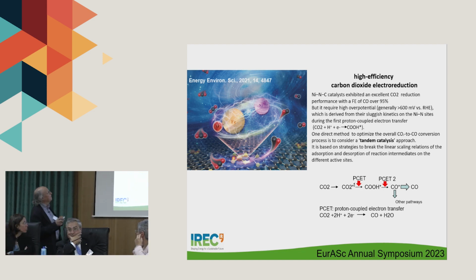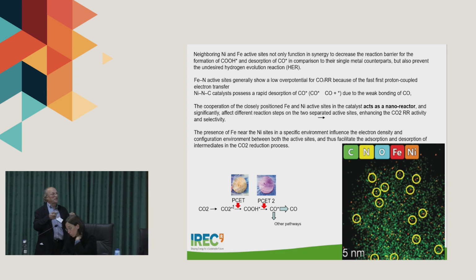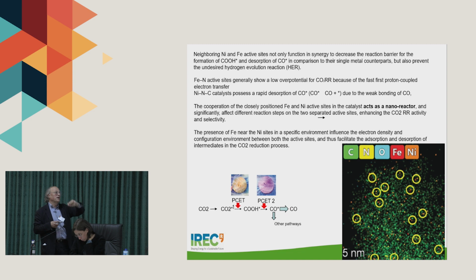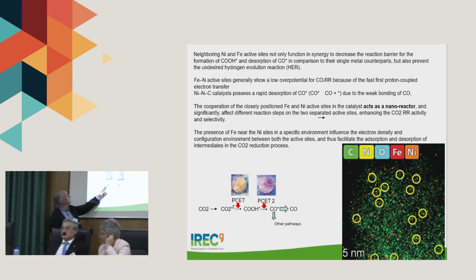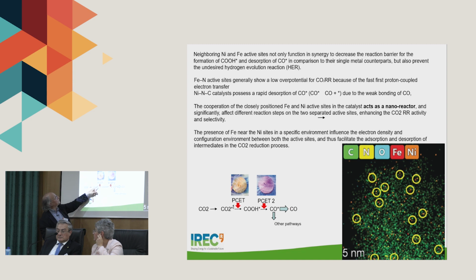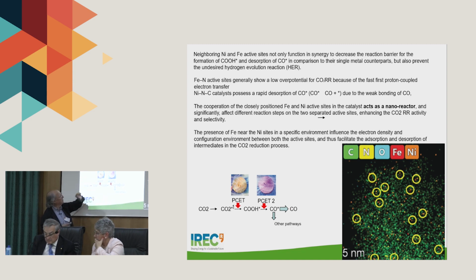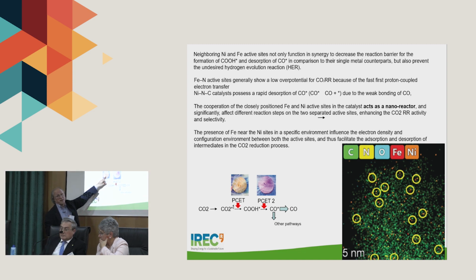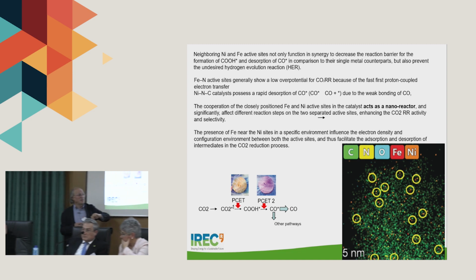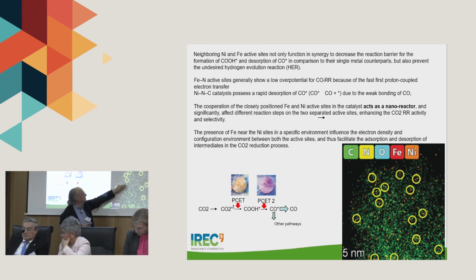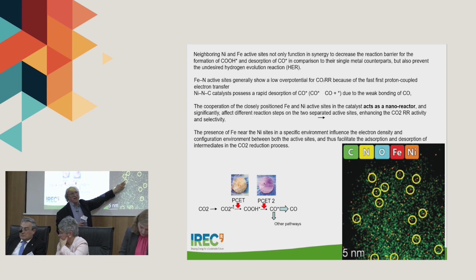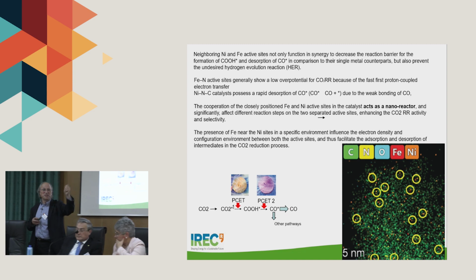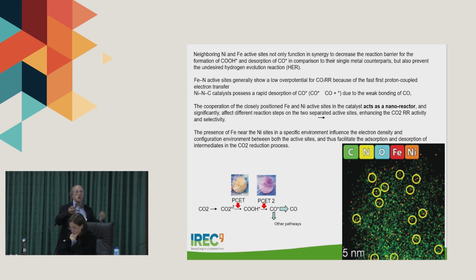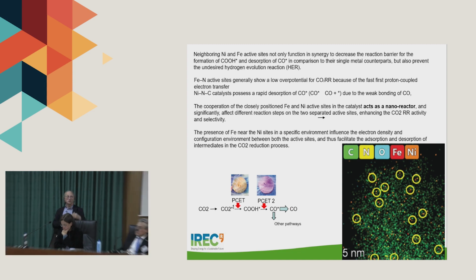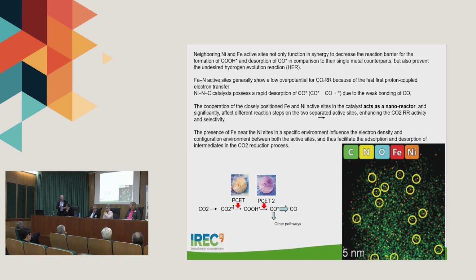For example, in this case, after analysis of the characteristics of the first step and the second step, we try to combine nickel and iron. And we arrive at the idea that for the first step, that is the proton-coupled electron transition, iron is better, because it has better parameters, and in the second step nickel is better. So the idea is that it's possible to make a synthesis getting 1 atom of iron, another of nickel together, just to stimulate this transition. Okay, this morning the colleague Hermenegildo was talking about the MOF. This is based on MOF design.